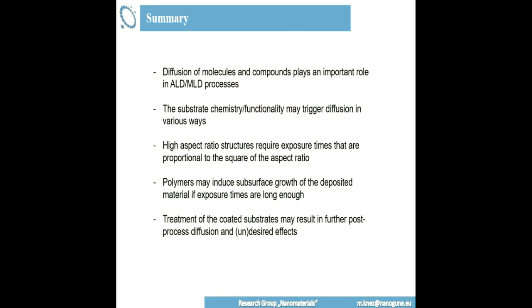That means what I showed here quickly was the Teflon. Teflon became brittle, although it was flexible before. Some of the things became mechanically tougher, more stable, whatever. Some things became worse. So your polymer which you are possibly handling while coating may change its physical or practical properties in an undesired way. It may also change the coloration, for example. So this can all happen if you infiltrate polymers. So if you don't want to have this, then you need to take, again, those measures to prevent this infiltration.